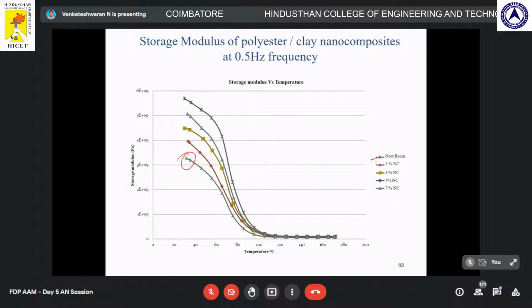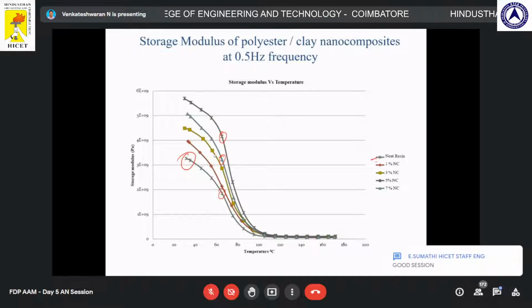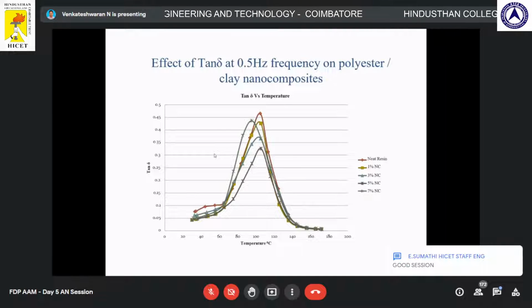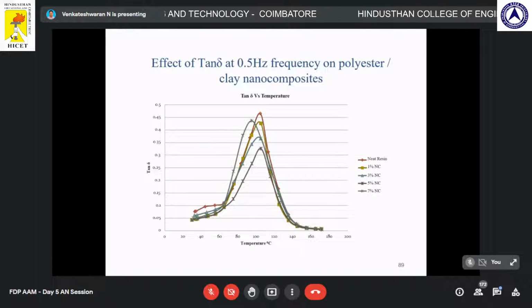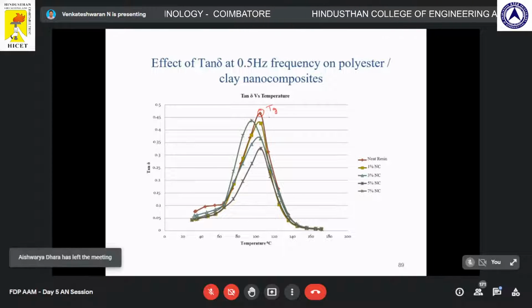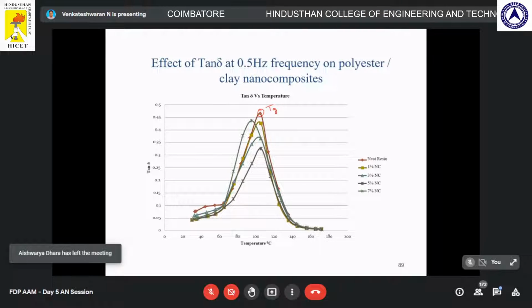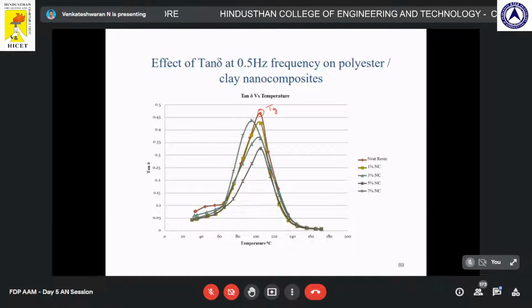And if we compare at the different temperatures, we are able to find out the storage modulus of the material, which increases with the addition of nano clay. Next, tan delta gives the glass transition temperature, that is the peak. The peak of this gives the glass transition temperature, and with the addition, there is a shift in the value. There is always a shift in the glass transition peak. This peak got widened. These curves got widened up.